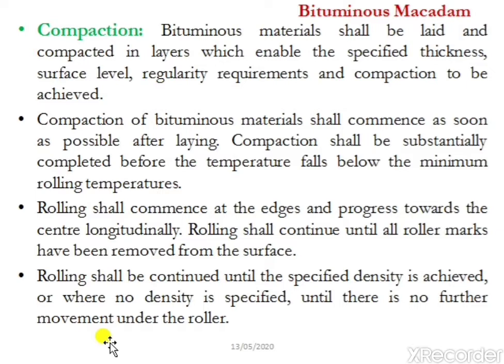Rolling shall commence at the edges and progress towards the center longitudinally. Rolling shall continue until all roller marks have been removed from the surfaces. So the compaction operation is achieved by using rollers, and the rollers start their operation from the edges of the pavement and move towards the center of the pavement in the longitudinal direction. The rollers should keep moving along the pavement until all the marks of the roller are removed from the surface. Once all the roller marks are removed, it is said that the compaction has been done to the specific point.